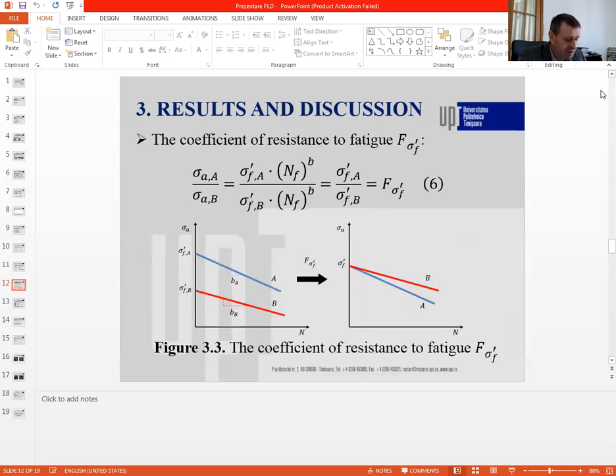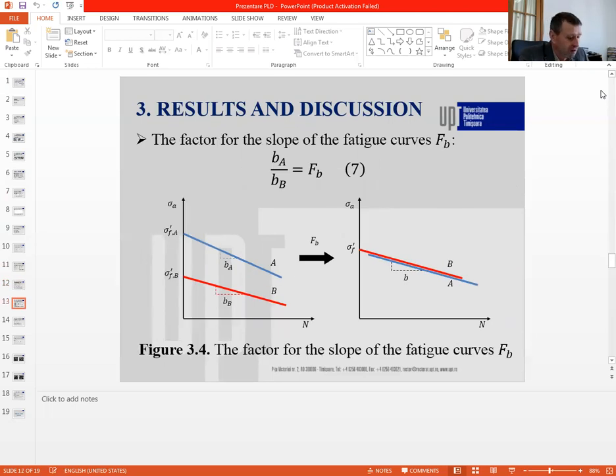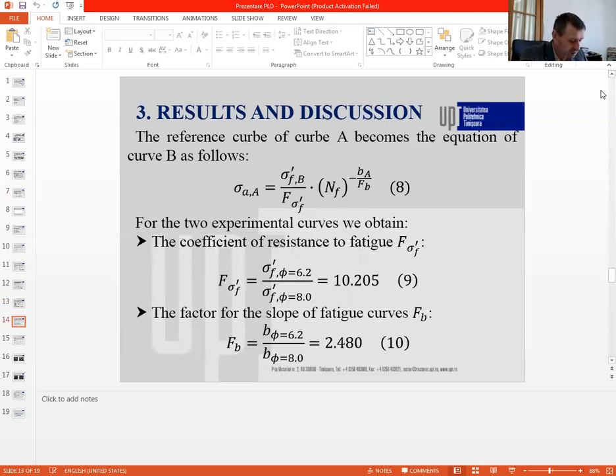The correlation is defined by two factors. Correlation of the fatigue curves so that they have the same coefficient of fatigue, equation 6. Correlation of the fatigue curves so that they have the same slope, FB, equation 7. Knowing the correlation coefficients, a master curve can be obtained that includes the dimensional effect and whose equation is equation 8. Analyzing the experimental results, we obtained the correlation factor of the fatigue resistance coefficient and, respectively, the correlation factor for the slope of the fatigue curves.